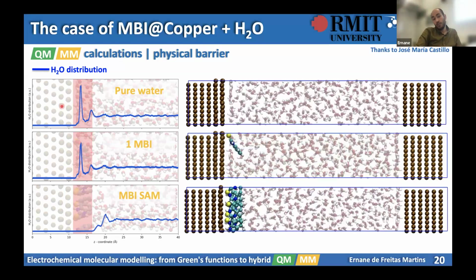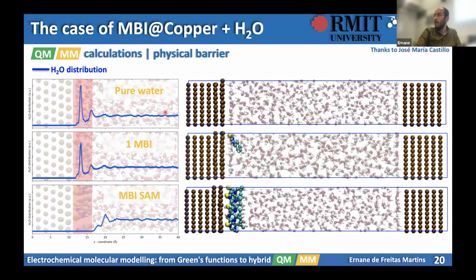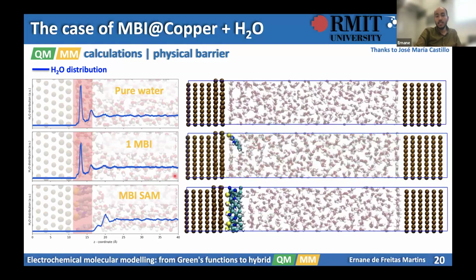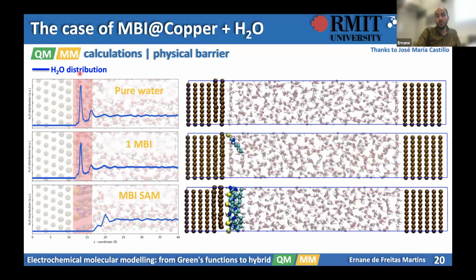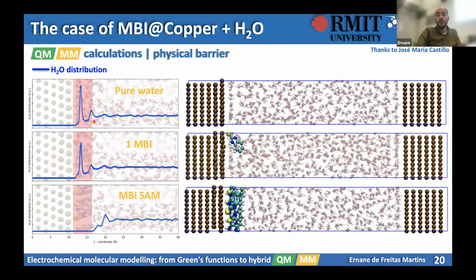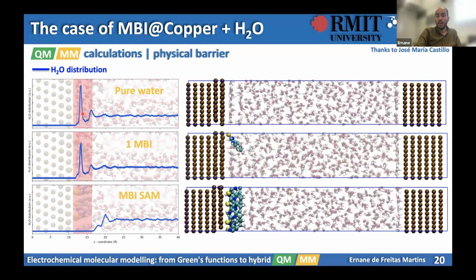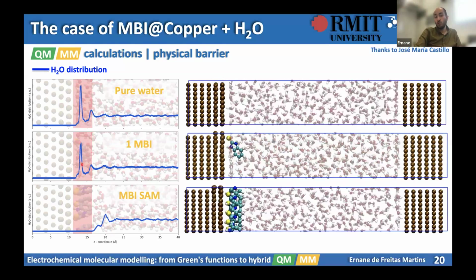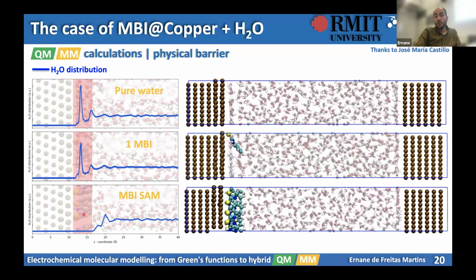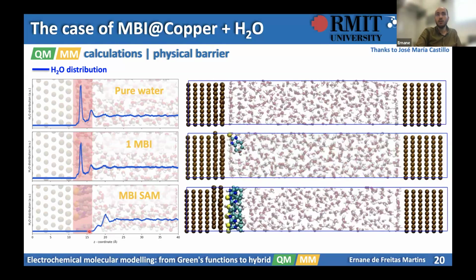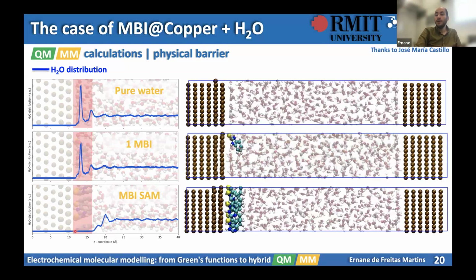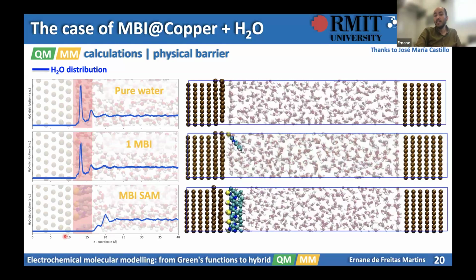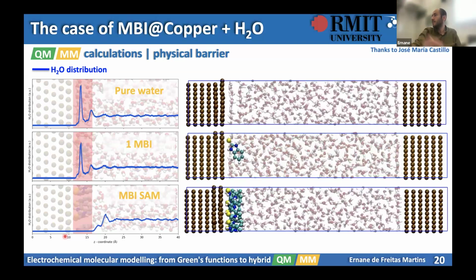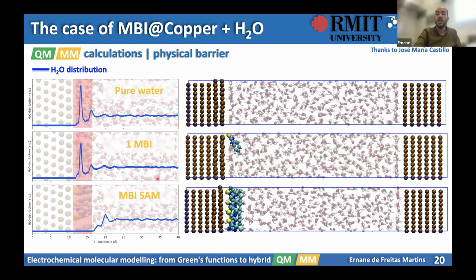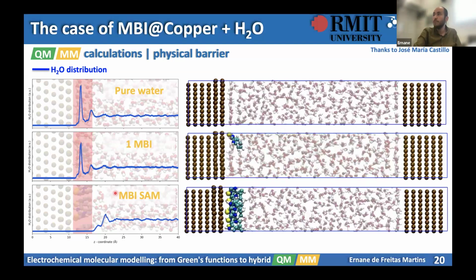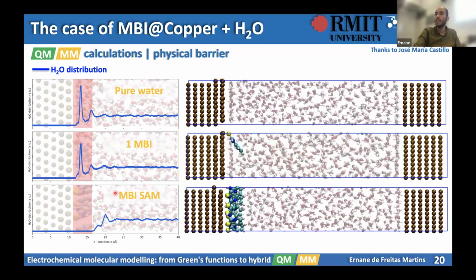So here you can see, first of all, the water is equilibrated at the bulk. And what we can see is that we have a structuring of water here that is strongly affected by the presence of the inhibitor. So going from one molecule to a full coverage, we see that there is no water molecule getting close to the surface, even in this case where the inhibitors could leave the surface if needed, because this is molecular dynamics. So the layer of inhibitors is stable and is protecting the metal from interacting with water.